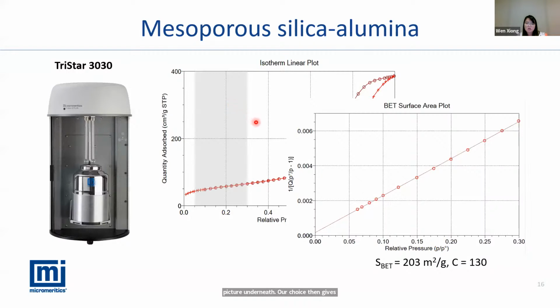When we apply the BET equation in the BET range of the whole isotherm, this is the BET range. Normally we use the BET range of relative pressure from 0.05 to 0.3, which I mentioned earlier, and I also highlight here in gray. Then we apply the BET equation and plot it in the linear form. This transformation to the linear form can be done automatically and easily with our instrument software. On the right corner is the result showing the BET surface area is about 203 square meters per gram, with a C value equal to 130. When we're talking about the BET surface area, we have 4 different criteria to fit when applying the BET equation. We are going to talk about this later.